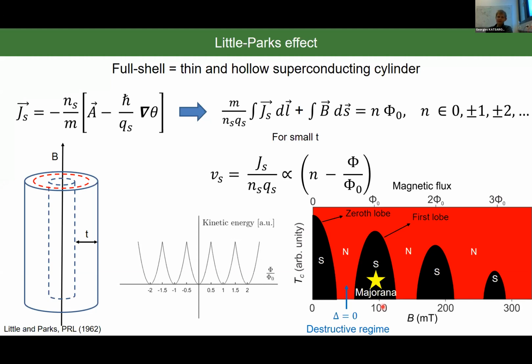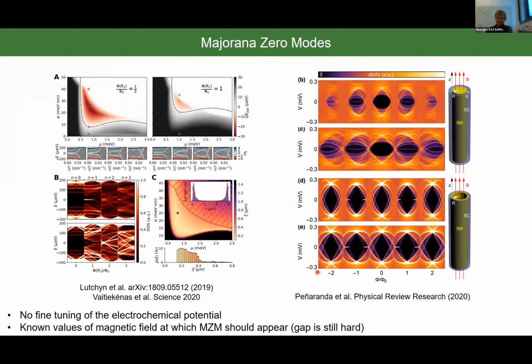So I told you we think that that material platform is an ideal platform for studying the interplay between Andreev bound states and Majorana physics. Why is that so? Because here there is no fine-tuning of the electrochemical potential, and actually you cannot fine-tune it because all electric field will be fully screened by the aluminum shell. And the additional advantage is that now you know exactly at what values of magnetic field you should be looking for the Majorana zero modes. And as I'm going to show you soon, actually at that value of magnetic field, your gap is still hard.